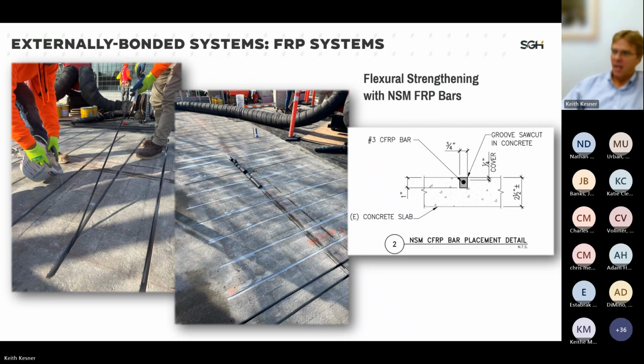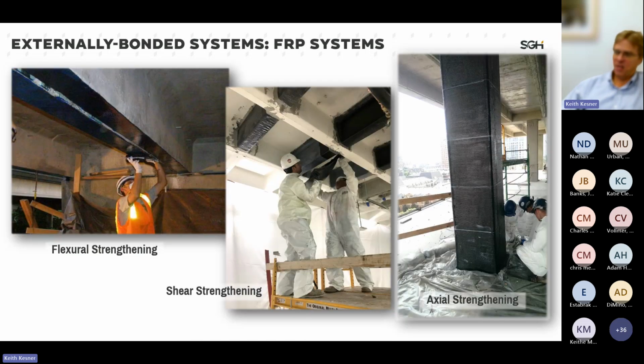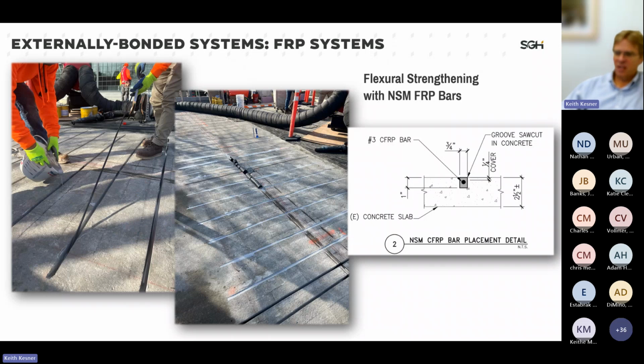And these can be internal or external. In the previous slide, they were all on the exterior, and they're using the epoxy to bond to the structure. When you're doing it internally, you're cutting a slot in the structure, and then you're using epoxy or other adhesive to bond the FRP bar back into the concrete structure.